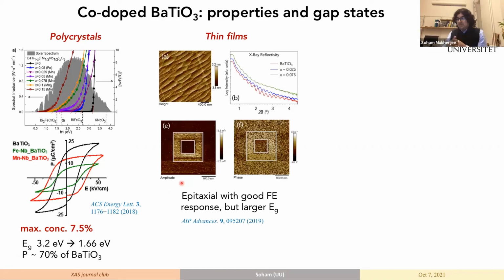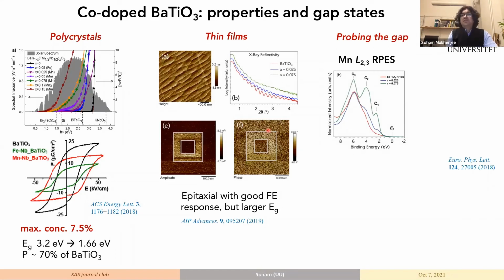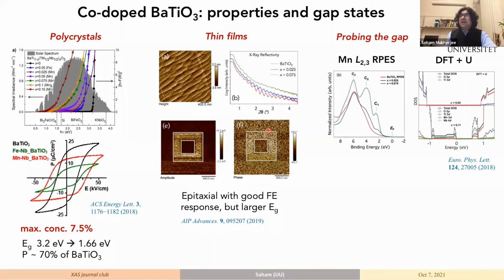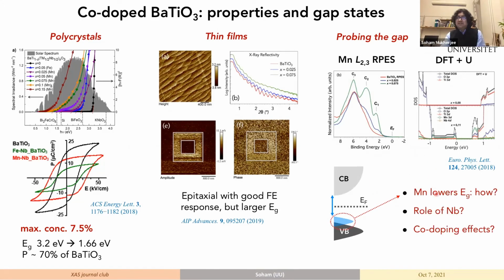We went ahead and made thin films at Chalmers in Gothenburg. The films were a bit off-stoichiometric, but they showed some ferroelectric response, and we are now in the process of trying to improve the films. But the materials could be made into good films. We went ahead and probed the gap, and this was one of the works which got published earlier. When we look at the resonant photoemission, we see that selectively the manganese states get enhanced, and the calculations also showed that manganese states are growing in the band gap of barium titanate when you dope the system. So we can clearly assign that the new states that have come up due to doping are related to the manganese states.